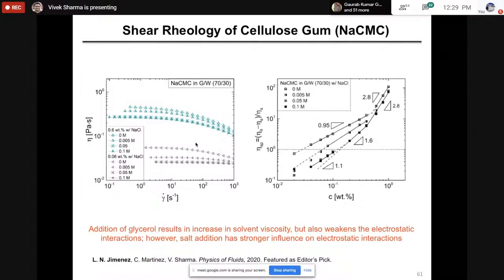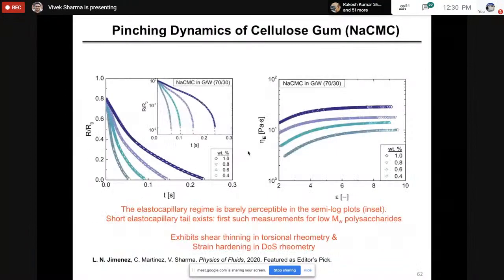But as you add salt, some of those charge interactions get screened, coils become smaller and smaller. So on adding salt, the overlap concentration, which is where this specific viscosity is 1, shifts to a higher value, and the overall viscosity also goes down. So shear viscosity gets affected quite a bit when you add even 0.005 molar of NaCl. Right? So this is something that's very important. Every time you're trying to make food formulations, we do add a certain amount of salt. And depending upon how much salt you like, your curry might turn out to be thinner or thicker just because of the thickener being a polyelectrolyte.